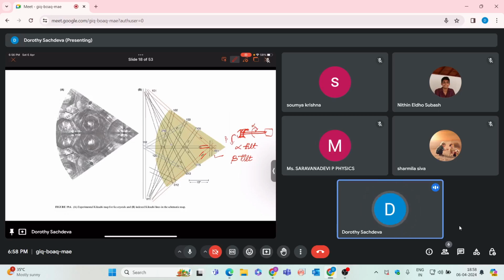So generally it's seen that when you are doing this alpha tilt, you are just rotating the goniometer itself like this, and in beta, suppose this is your specimen holder, you are completely tilting it in this direction. So then you are changing the Z also. Just the Z value is also changed. So when you are doing this beta tilt, then you always need to correct your Z value in order to get a good quality image, or in order to understand whether you are going in the right direction or not.